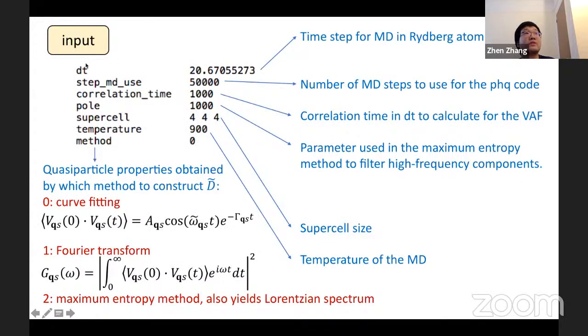Finally is the input file. So first, dt is the time step for MD simulation in Rydberg atomic unit. Step MD used is the MD steps we want to use for the calculations in the code. Correlation time indicates the correlation time to calculate for the velocity autocorrelation functions in unit of dt. Pole is the parameter used in the maximum entropy method to filter high frequency components. Later, I will talk about the maximum entropy method. Supercell indicates the supercell size we used in the MD. Temperature is simply the MD's temperature. And finally, by setting the method tag, we can select quasi-particle properties obtained by which method to construct the effective harmonic dynamical matrices.